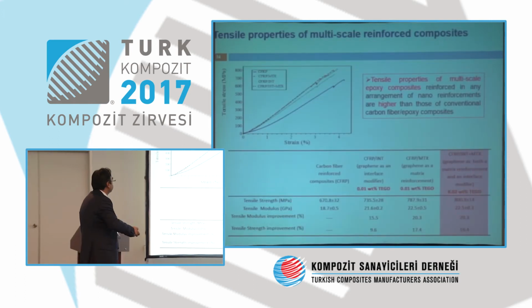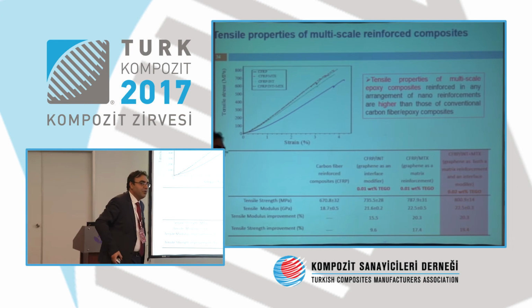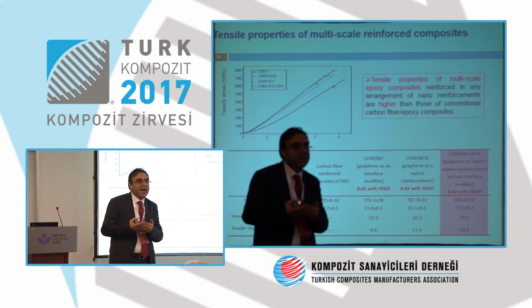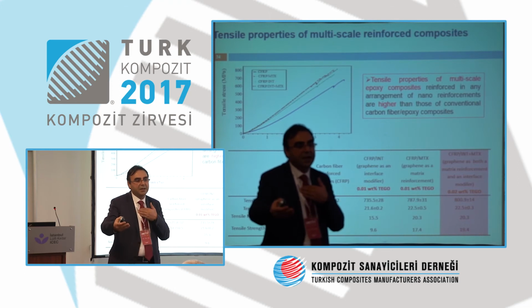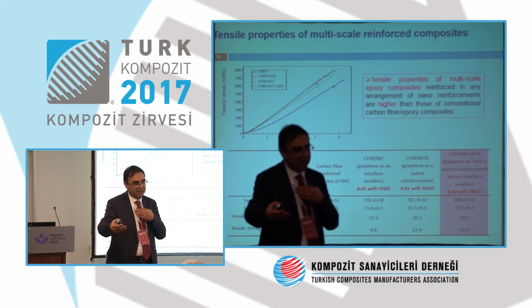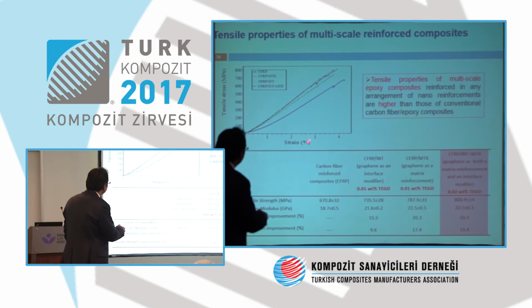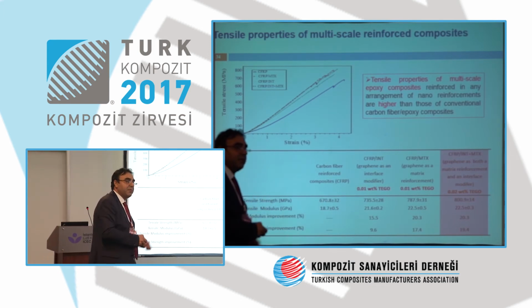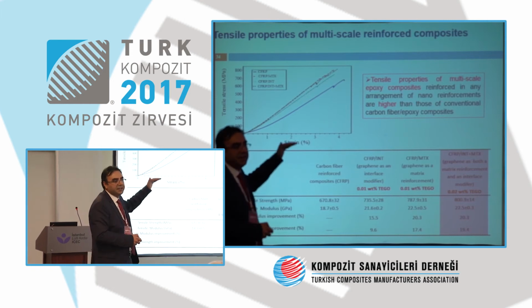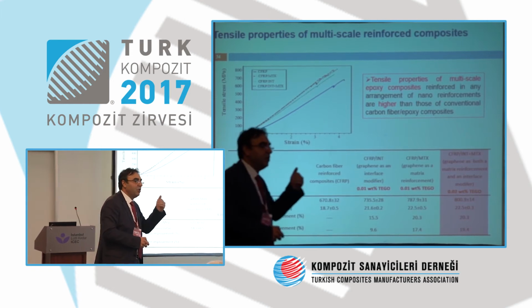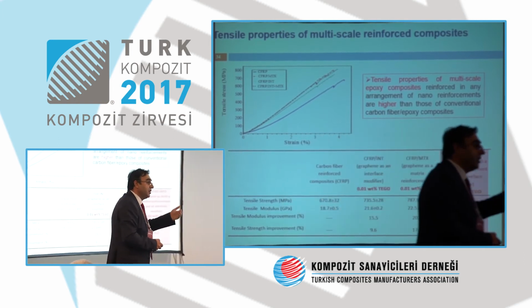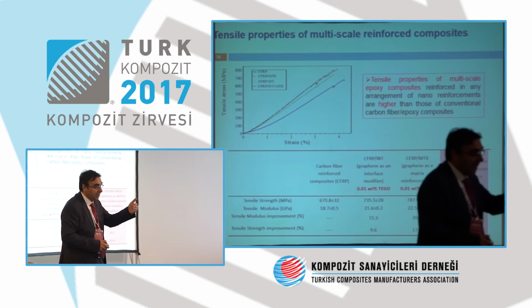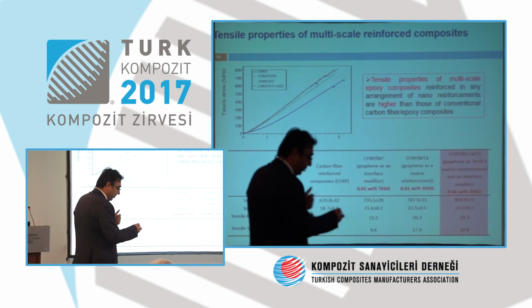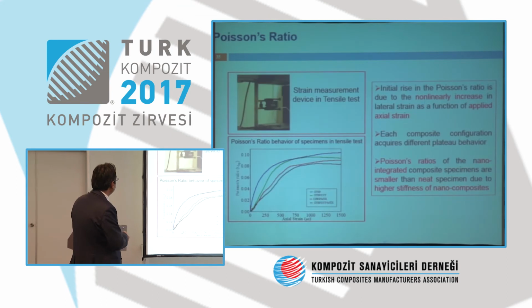And of course, we look at the tensile properties. The improvement is not that significant because the primary load-carrying agent is the carbon fiber reinforcement. So although there are improvements, around 20% here, in comparison to the flexural it is still half of it. So with the addition of nano-integration, if you do that in an engineered part, the aim should be increasing the flexural strength, toughness, and also impact attributes, not the tensile property. So this is the takeaway lesson that we can mention.